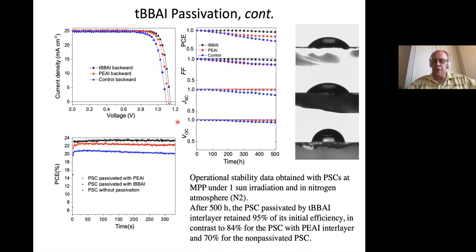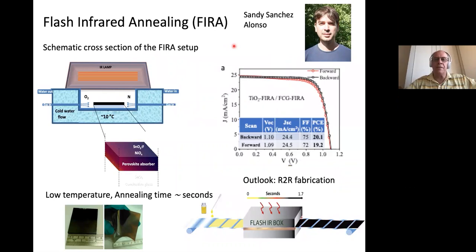I'm starting to come to the end. In terms of fabrication, there's a lot of development on how to produce in large scale. We are not making large scale modules and so on, but we are working on what we think is an interesting technique to fire the perovskite in seconds. Typically we anneal the perovskite film at 100 degrees for half an hour or so, or maybe less. But here you can simply take your perovskite film, illuminate with an infrared light source, and form your perovskite film in a matter of seconds or even less.